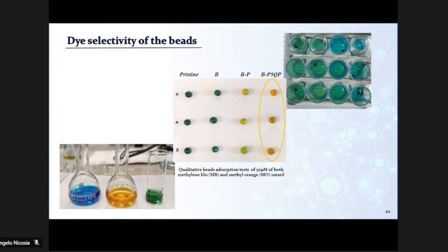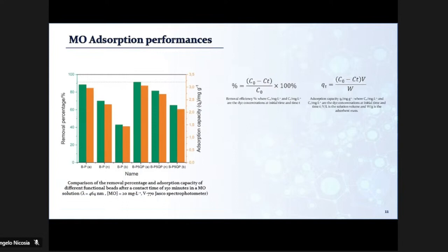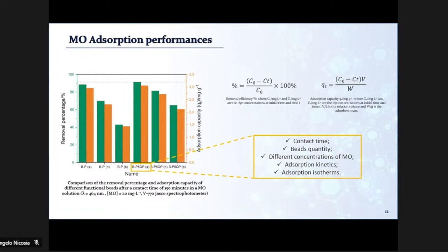This is due to the electrostatic effect of the bead, because it's positively charged for the presence of quaternized amino groups, but also protonated amino groups for the acidic environment of the coagulation bath, but also to possible host-guest interactions between the pillararenes and the methyl orange. We, of course, studied better the absorption performances of all the beads, employing UV measurements and a 20 milligram per liter solution of methyl orange. And again, we can see that the P5 based beads demonstrated the best absorption performances.